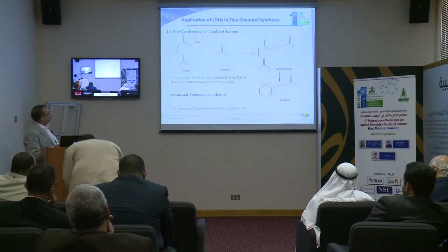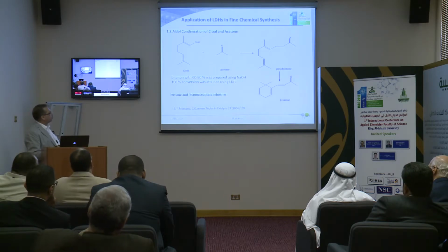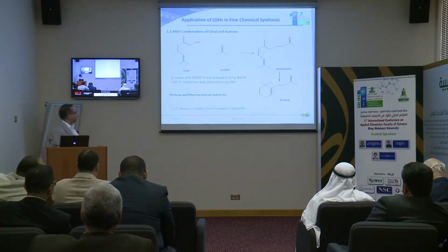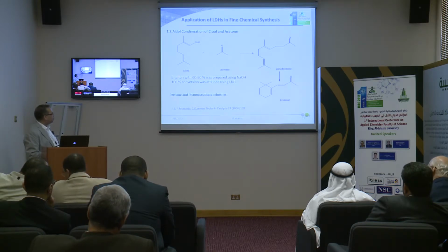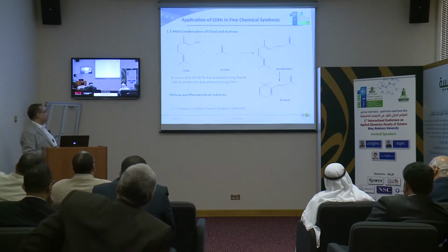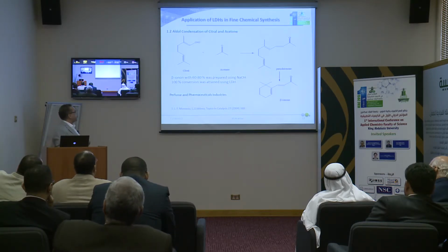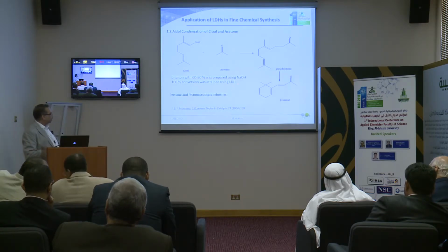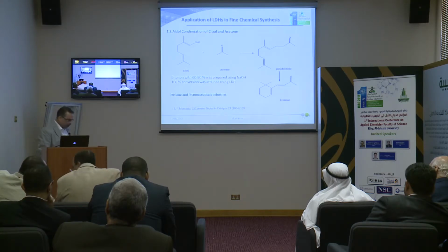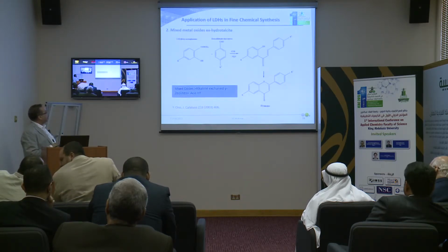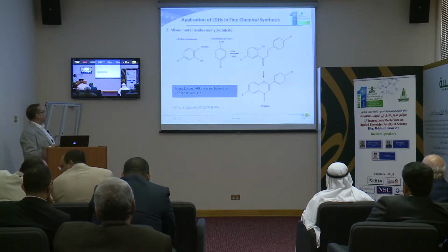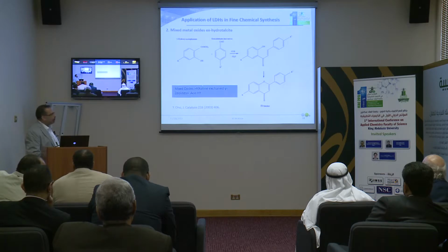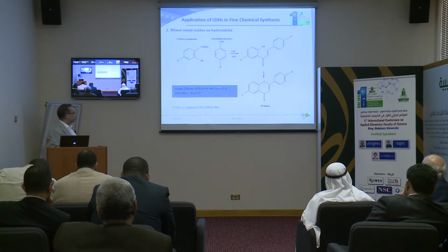Applications in fine chemicals also include the aldol condensation of citral and acetone in order to obtain beta-ionone with its wide applications. Beta-ionone at about 80% was prepared using sodium hydroxide. 100% conversion was attained by layered double hydroxide, so you can replace the soluble bases by the regenerated layered double hydroxide, as well as get 100% conversion using this smart material. For the mixed metal oxides, the hydrotalcite, which has more Lewis basic sites, found nice applications, better than the alkaline-exchanged Y zeolites as well as the acid HY zeolites, for the formation of flavanone.